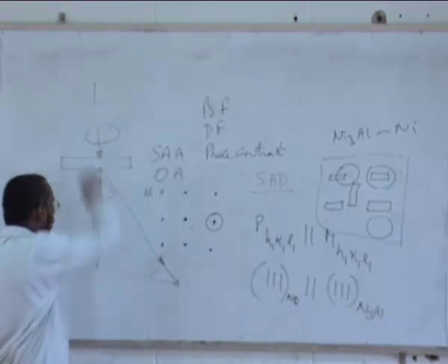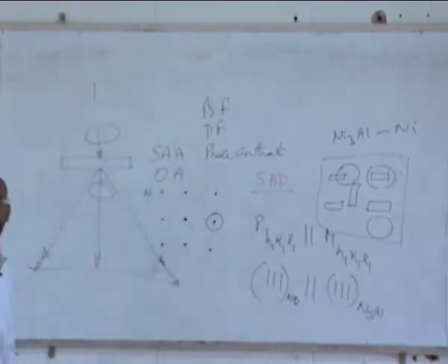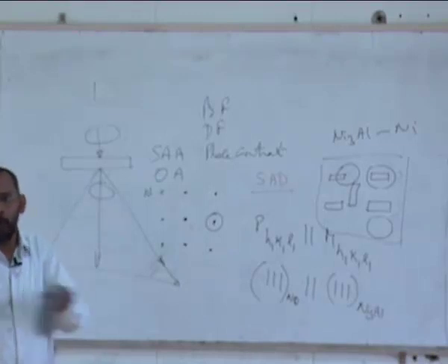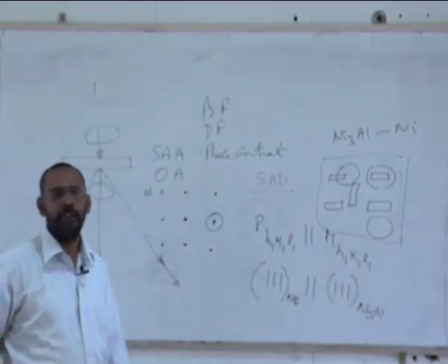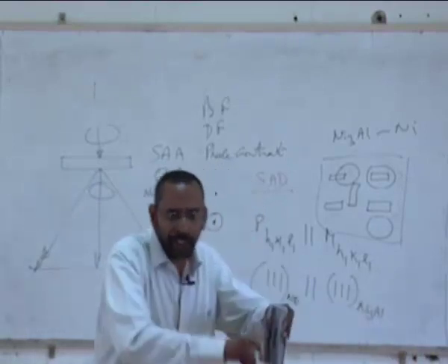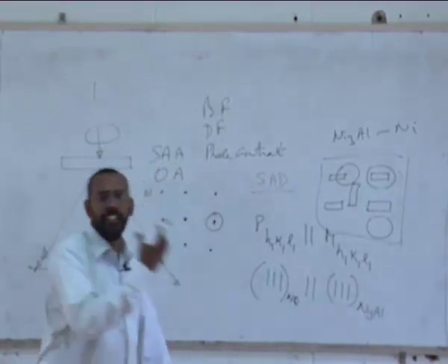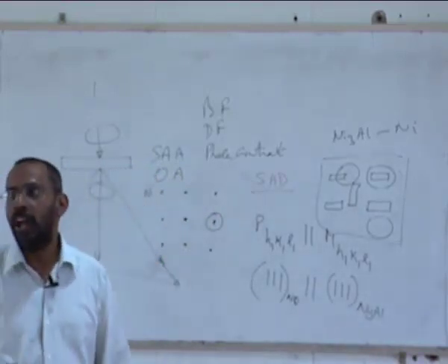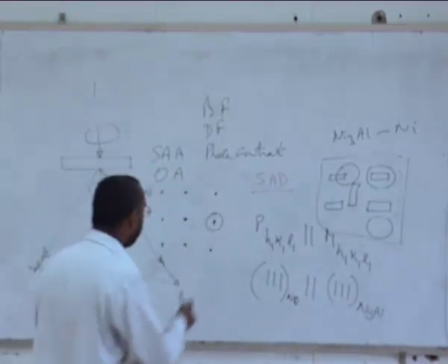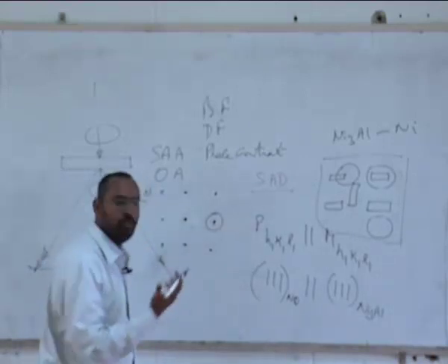The second possibility is move the diffracted spot to the center. There is an optical axis, okay, to this whole diffraction pattern. There is a center for the optical axis. I can move my diffraction pattern, and there are ways of doing that in TEM, and I can move that and bring the diffracted part to the center, and this is what is called centered dark field image. And if I do this centered dark field image, or bringing this here or moving that thing there, one of these two can be done.